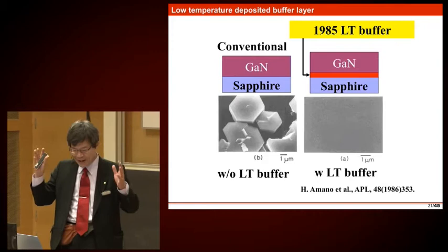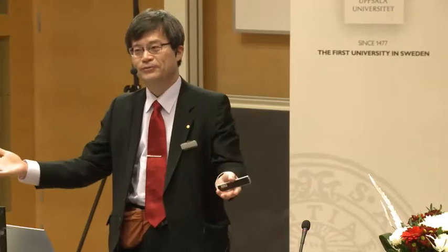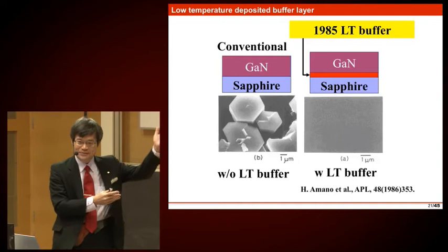But when I went to Professor Akasaki, he was so cool. He said, maybe the surface morphology is not enough. You should measure other material properties like crystalline quality, electrical properties, and optical properties. Then I checked all the properties and found that all of them were superior to every other previous report. So this technology became worldwide, and fortunately, all the people use this low temperature buffer technique worldwide.